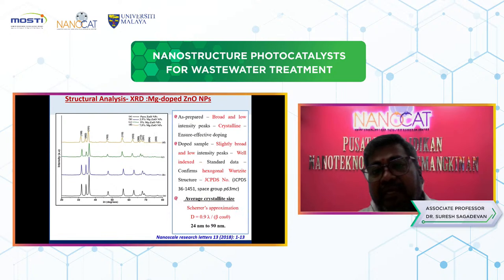And next, we worked on the magnesium doped zinc oxide nanoparticle. As I mentioned, these are XRD patterns with various doping concentrations. This one we tried with 2.5% to 7.5%. Why did we choose this kind of percentage? In the literature, they tried different ones, and nobody has done this kind of percentage. We tried with 2.5% increments.